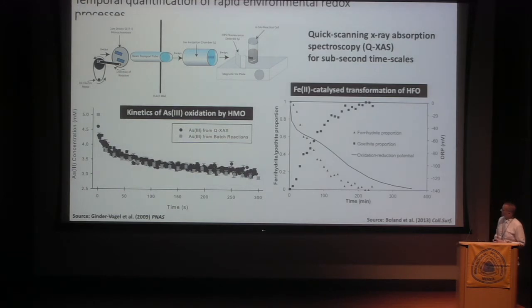This was a study that looked at iron 2 catalyzed transformation of ferrihydrite and getting full EXAFS scans out to k of 15 inverse angstroms in 20 seconds. So getting a full EXAFS scan in 20 seconds. And this is for a bulk material where you have lots of iron. We could have a discussion about how you would do this for trace elements, which are not going to get full EXAFS scans in 20 seconds per se.